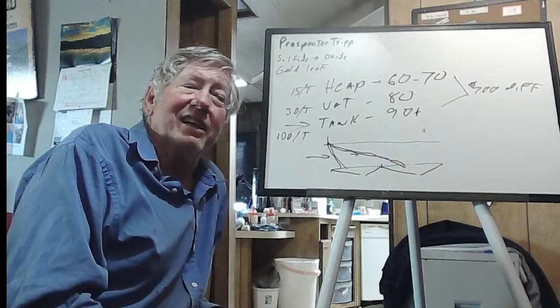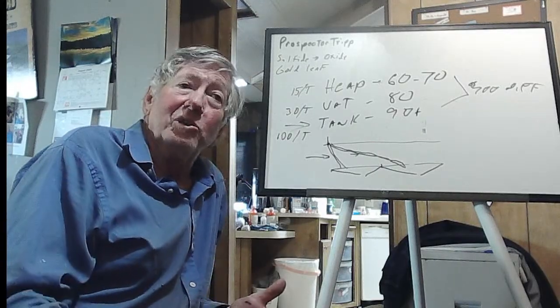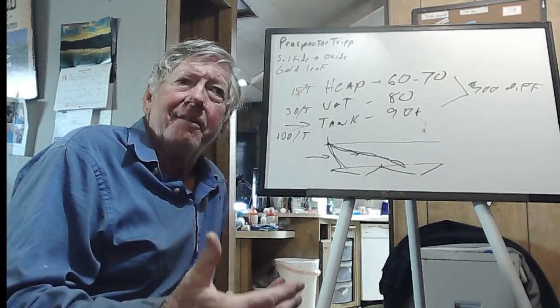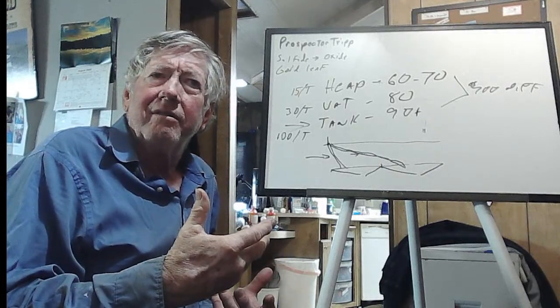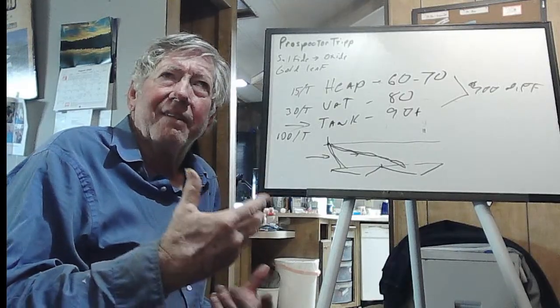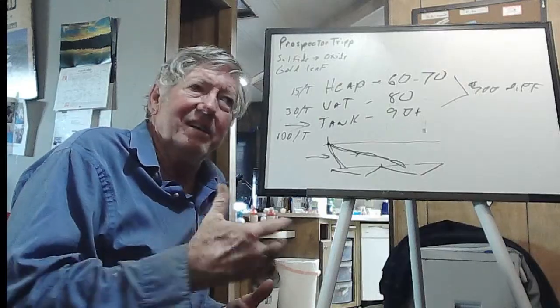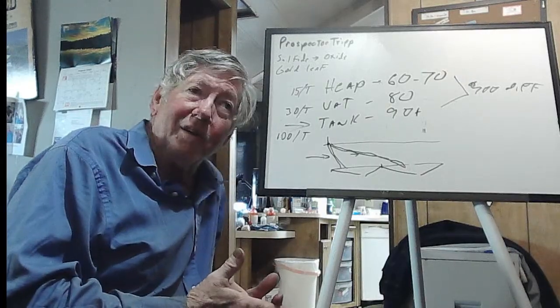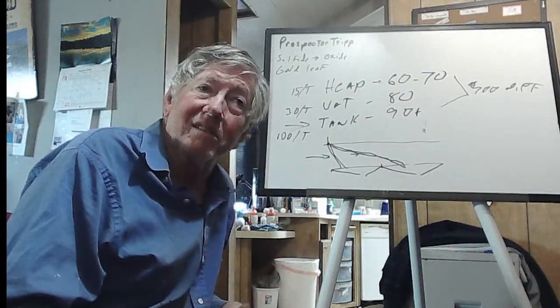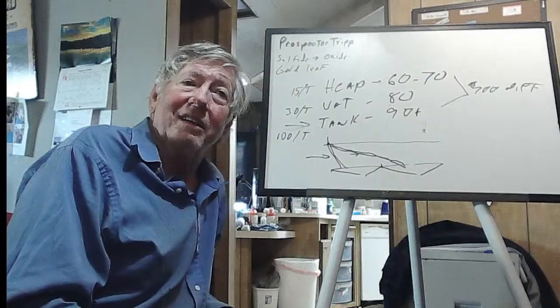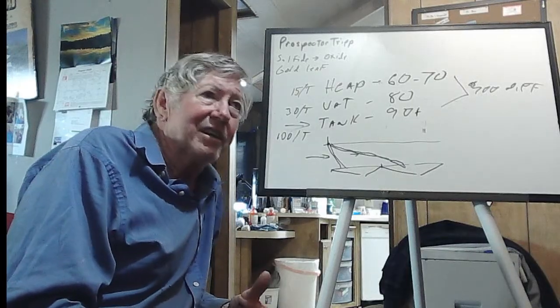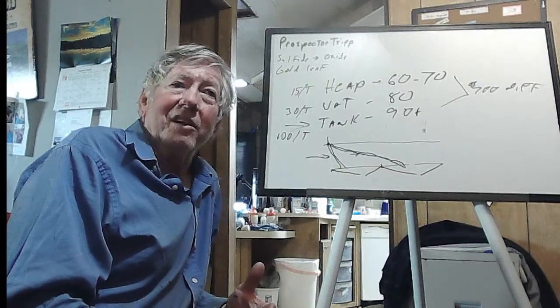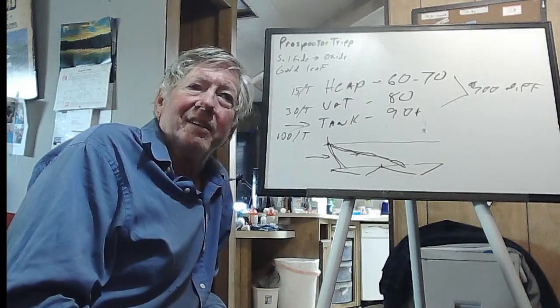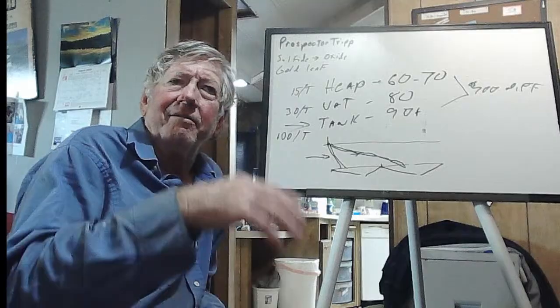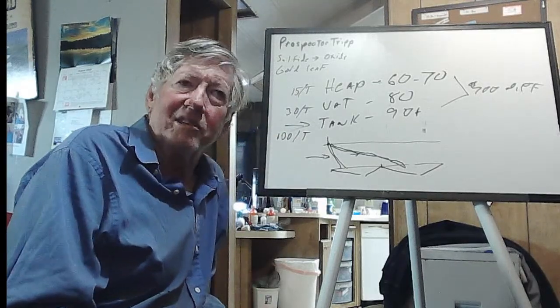Once I do that, then I still got to get the dissolution stuff. That's after the roasting. So do we use bottle rolls? Do we use, like, a cement mixer? Depends on how much material we have to deal with. As a general rule, if I had my druthers, I'd rather go with, like, 20-pound bottle rolls than a 60-pound cement mixer charge.